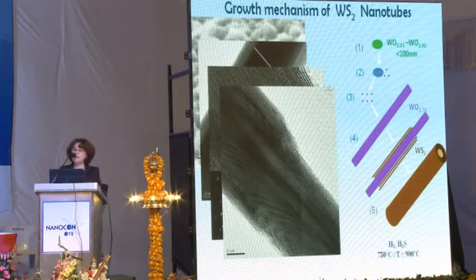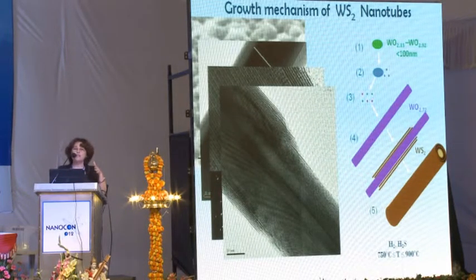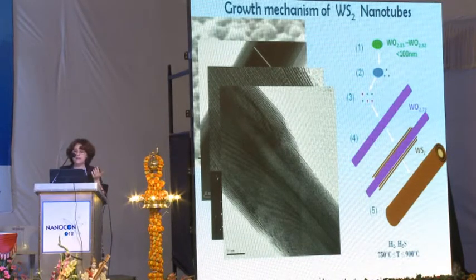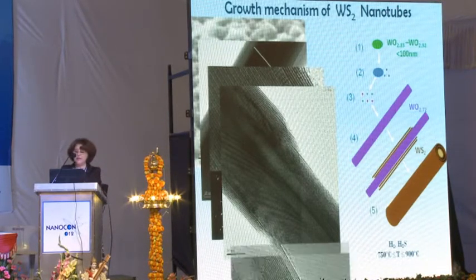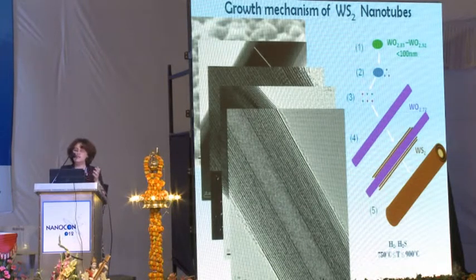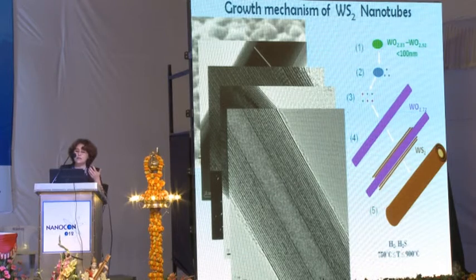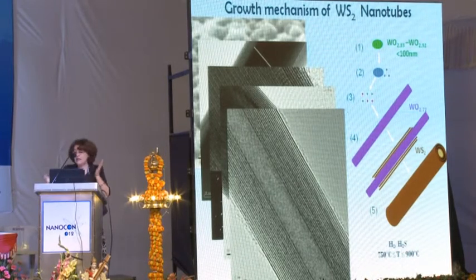This is another picture. In order to get these pictures, I stopped the reaction after 2 minutes, 5, 10, and so on, and studied this material in a microscope. And actually, after 6 hours of the reaction, depending on the size, we can convert all oxide whiskers to this sulfide. It is a very interesting reaction, but I cannot explain it to you.